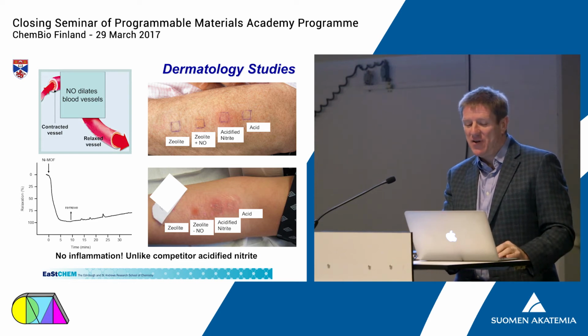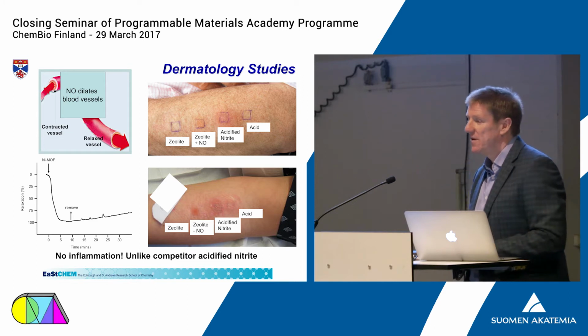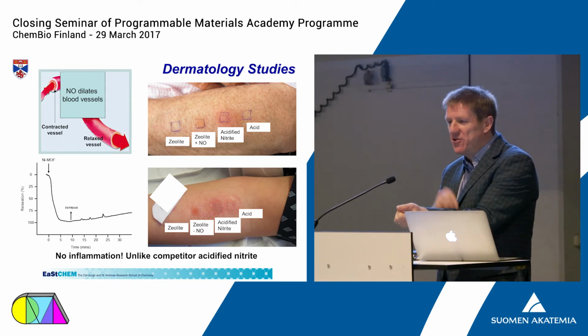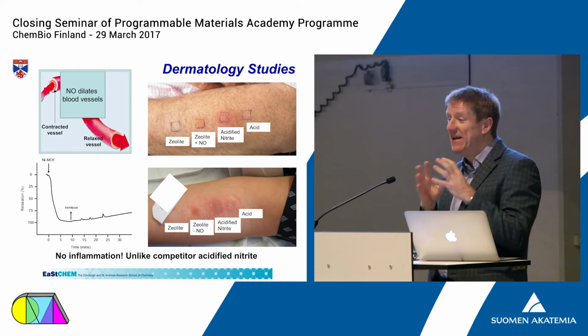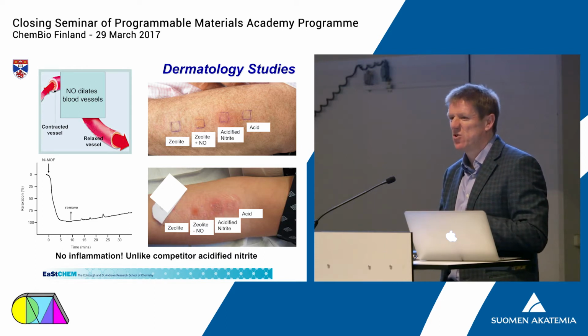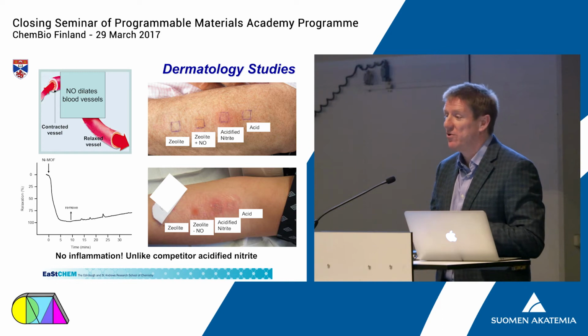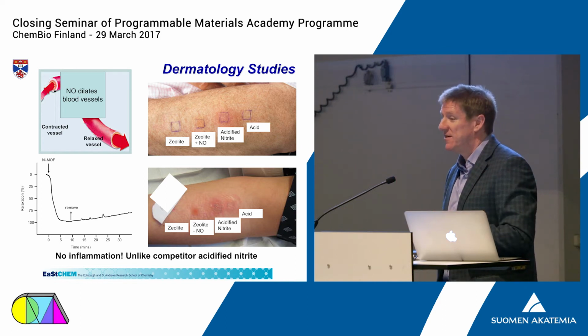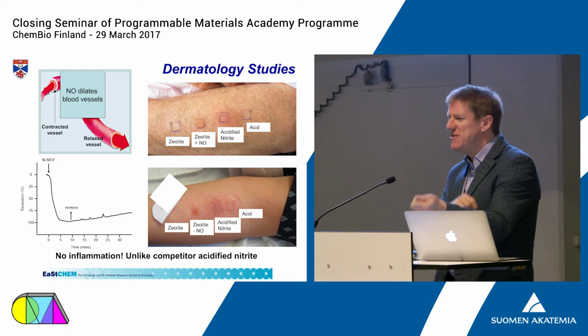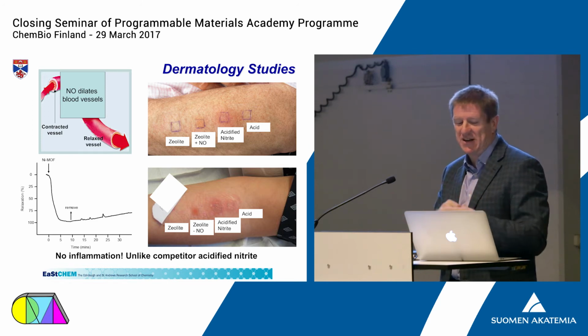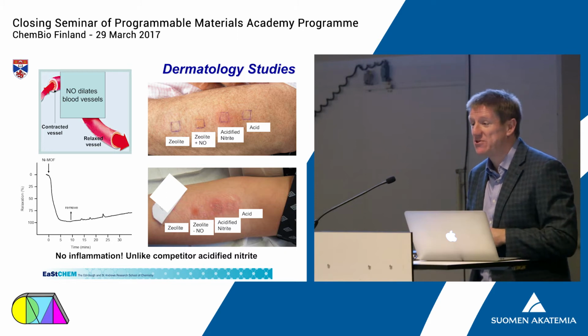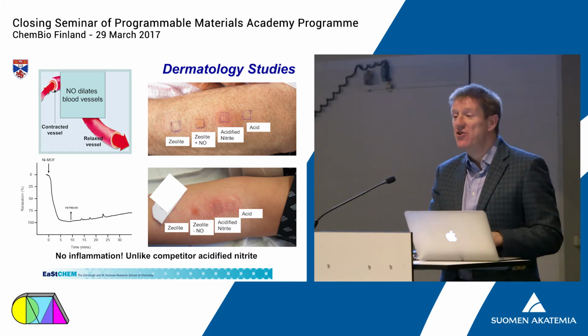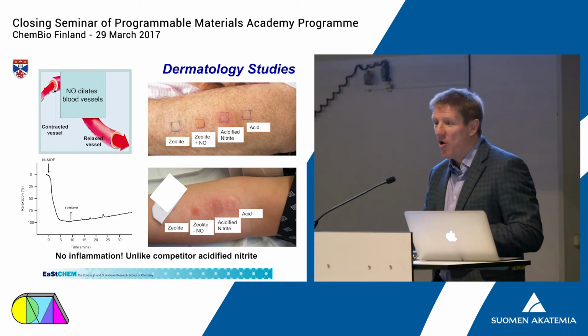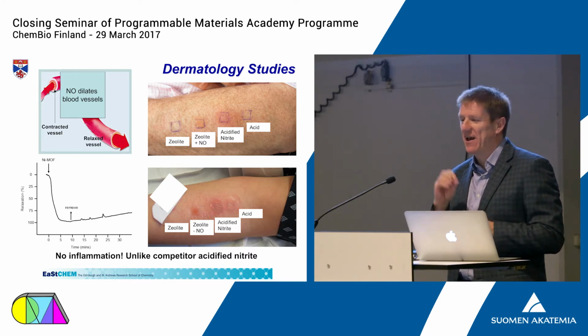If we then have a material which delivers nitric oxide, I don't know if you can see at the back, there's a little square of red there. That's simply the nitric oxide going through the skin and opening up the blood vessels, so you get a little bit more blood flow. It's called erythema, where you increase the blood flow and you get a bit of redness, right? Just because there's more blood flowing through the skin. And you can measure that using laser Doppler techniques, and you can measure exactly how fast and how it happens. And we can sort of see that there is no adverse reaction, no inflammation caused.